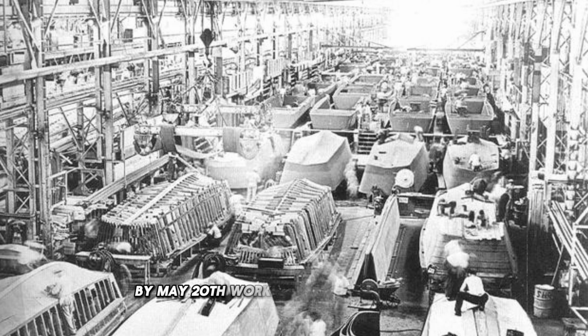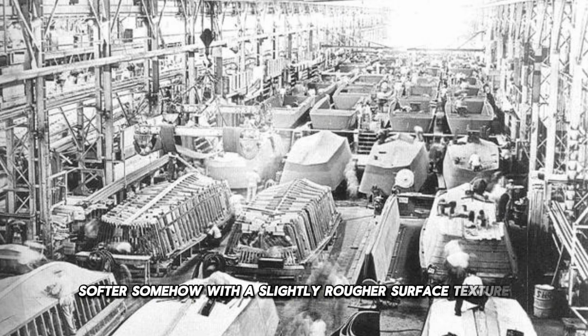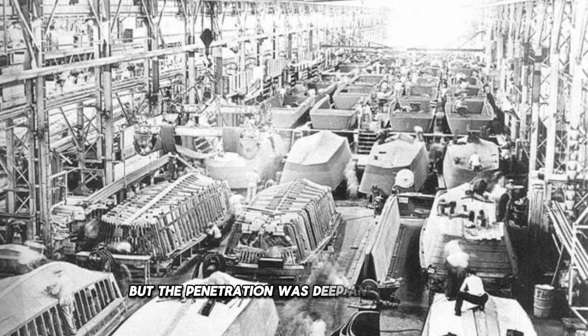By May 20th, working 4 hours per night, they'd completed modified welds on all 3 forward bulkheads at the 20-foot interval test sections. Paxton examined each weld personally, looking for the telltale signs of incomplete fusion, porosity, or cracking. The beads looked different from standard welds, softer somehow, with a slightly rougher surface texture, but the penetration was deep and consistent. The real test would come when 472 hit a mine. Paxton desperately hoped that test would never happen.